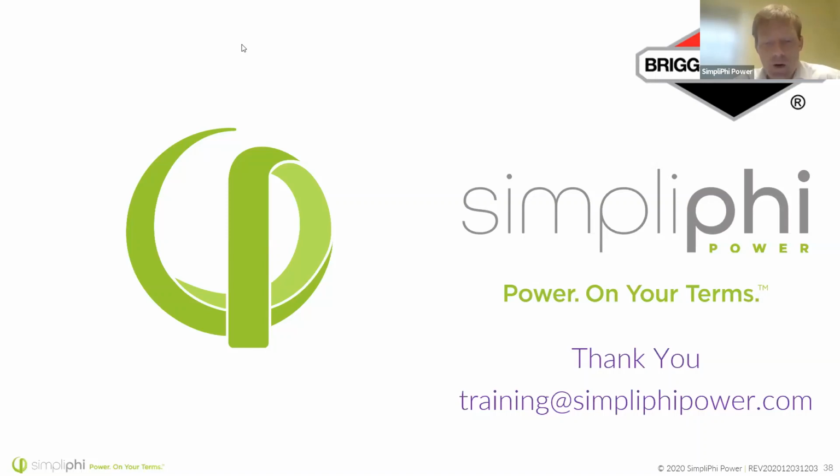Robinson asks, please, what do I mean by C/2? The C/2 is the charge rating of a battery. Every battery has a capacity to it, but there are important things to consider. You don't want to just consider the capacity of a battery. You also have to consider how quickly you can get that energy out of the battery. The capacity of a battery is how much energy is in the battery. The C rating of a battery is how quickly you can get that energy out of the battery without damaging the battery cells. You wouldn't want to take a AA battery and try to get 1,000 watts out of it. It wouldn't make any sense. As the capacity of a battery increases, the rate at which you can get that power out of the battery also increases. So a C/2 rating really means being able to fully discharge the battery in 2 hours.